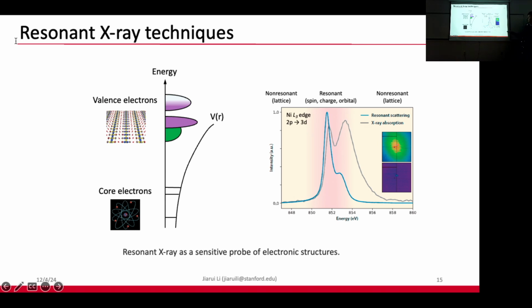This measures how much the photon is getting scattered by the electrons. And you also see an even sharper enhancement here. This measurement is taken at a magnetic Bragg peak. So at resonance, you see a clear magnetic Bragg peak, a very clear diffraction Bragg peak. But when you tune a few electron volts away in photon energy, while keeping the same Bragg condition matched, such a signal just goes away.